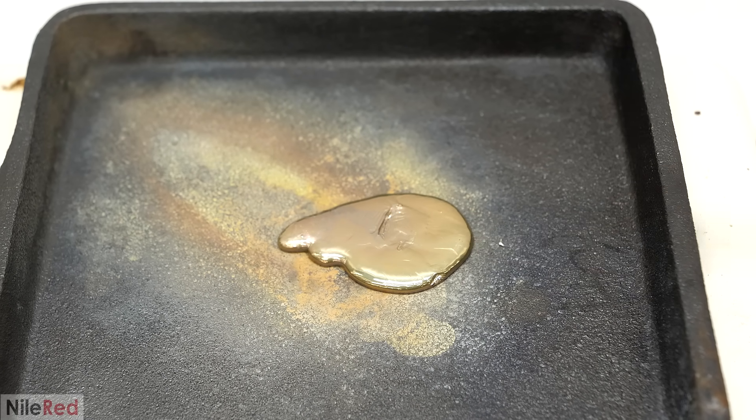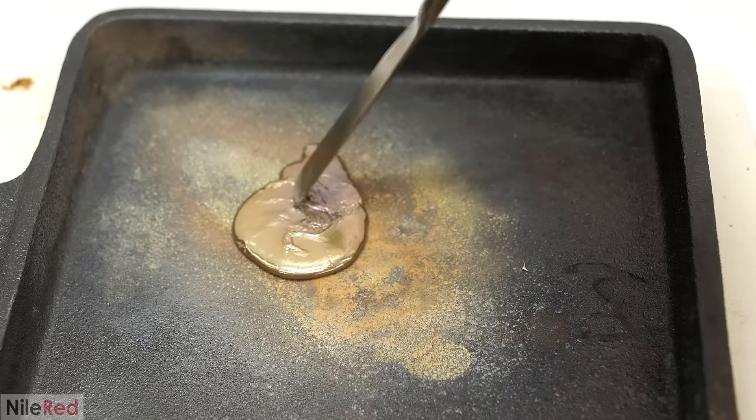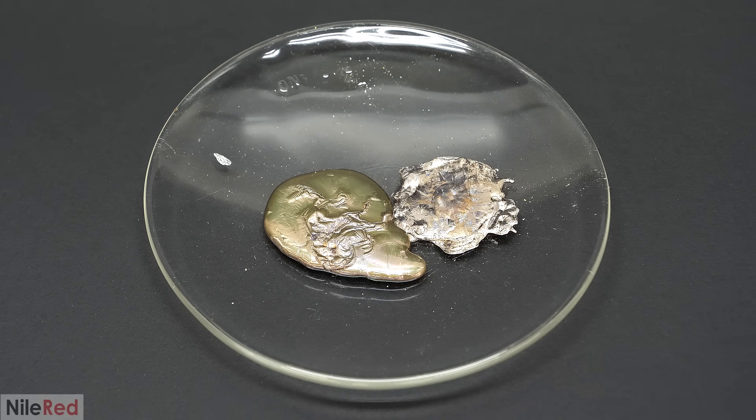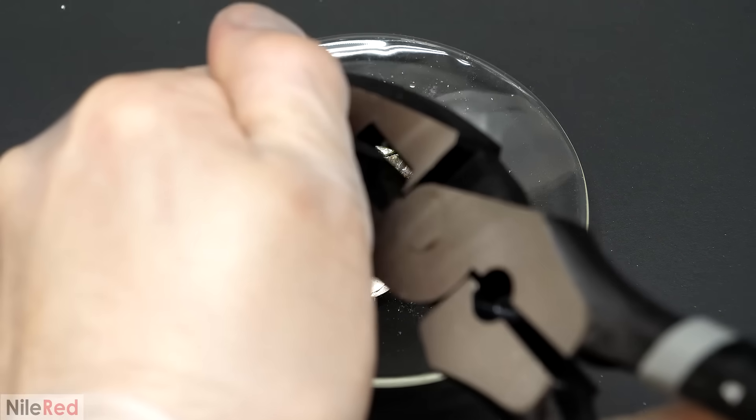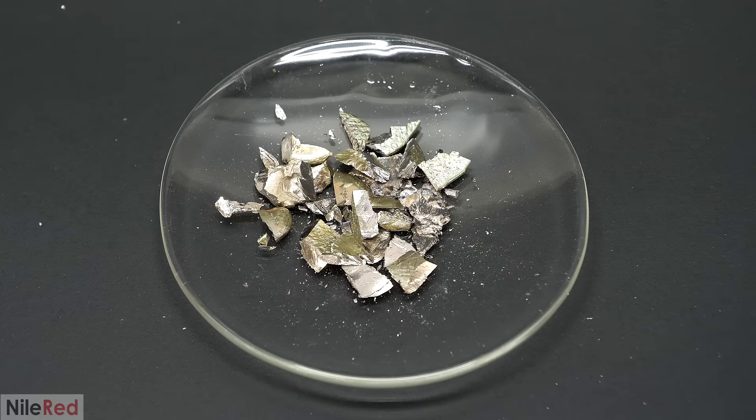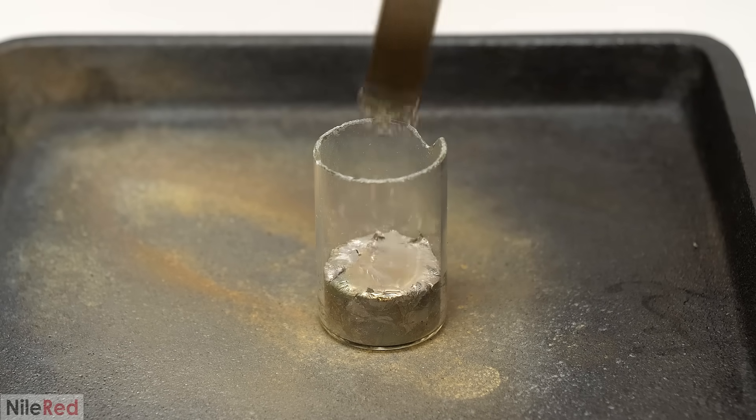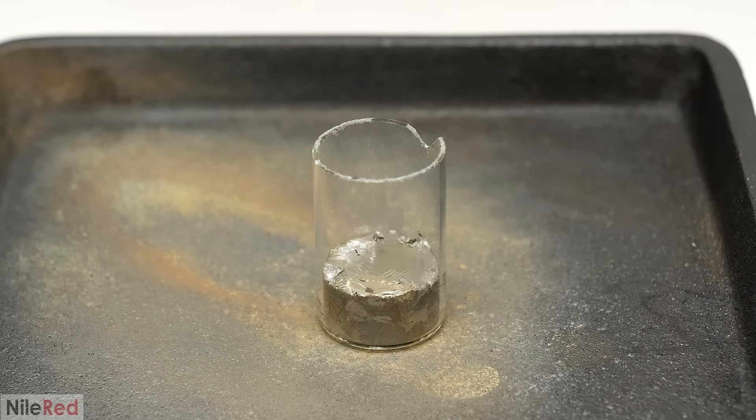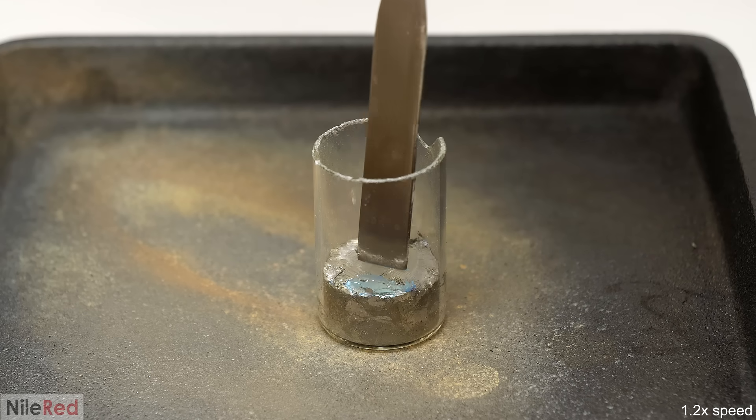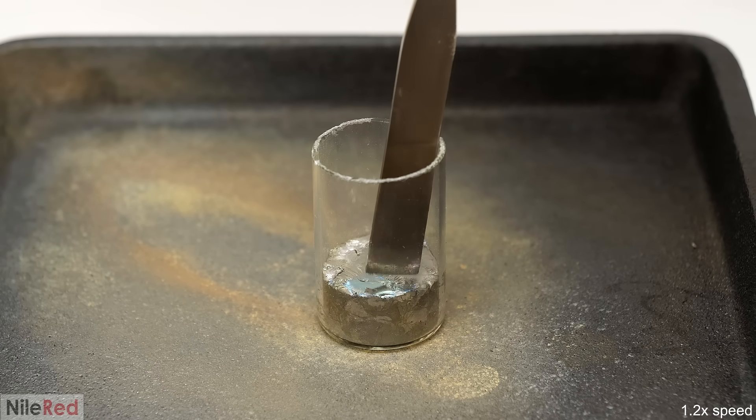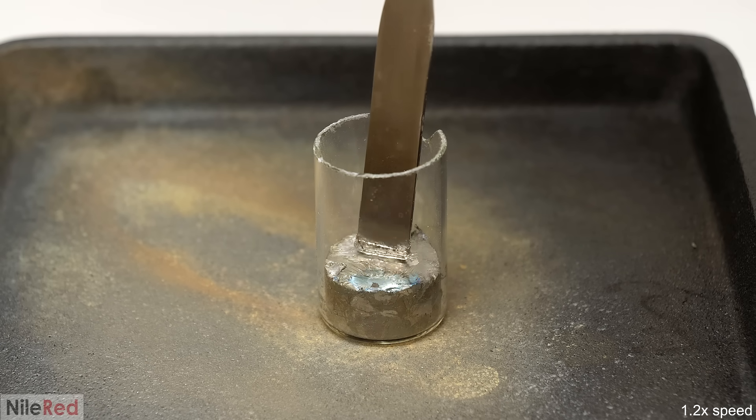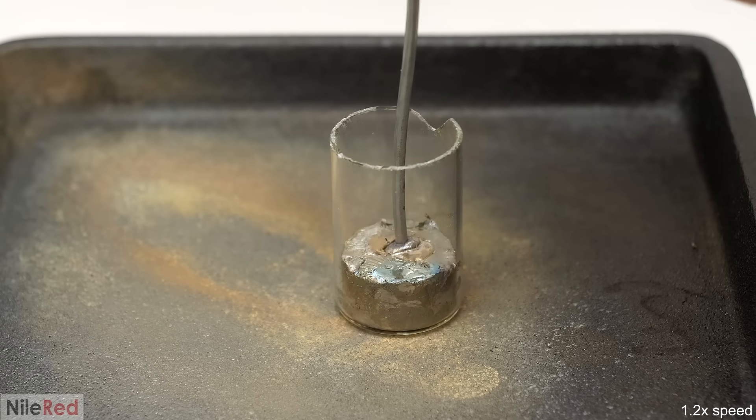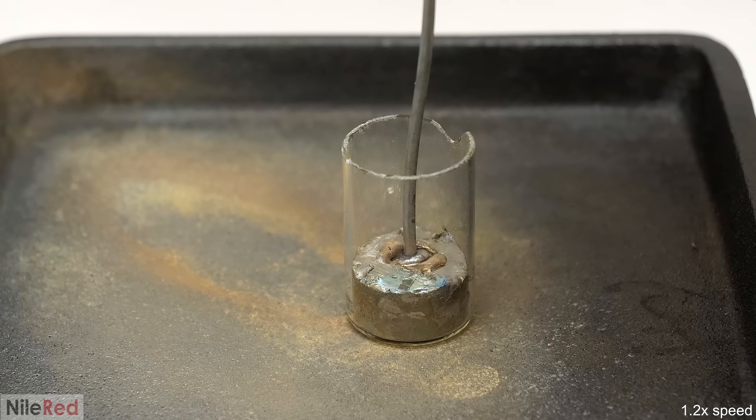I tried peeling off the bismuth, but it was still too hot, and I had to wait a few more minutes. It was kind of still liquidy at that point, but it was solid enough to separate. I also recovered a small amount of bismuth from the junk that didn't crystallize in the vial. Instead of using a hammer this time, I just used pliers and I broke it into pieces again. Then like before, I melted it down, skimmed the top, and waited for it to cool. My goal here was to do the same thing again, but I wanted to wait a bit longer so that more would solidify. However, I started to notice one major issue, and I think things were just cooling way too quickly. For proper crystals to form, it has to cool relatively slowly, but there just wasn't enough metal here to do that. There was little to no chance that anything decent formed here, so at the last minute, I decided to try something else.